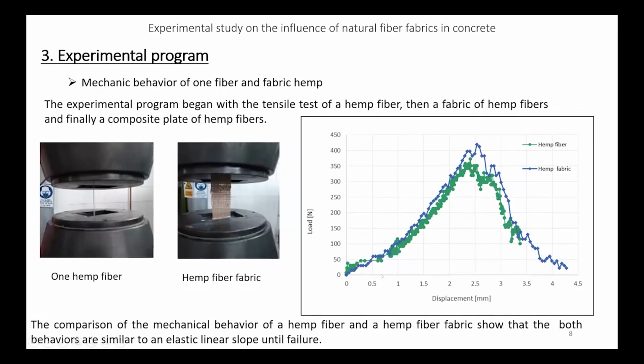You can see here some results for the tensile test of one fiber of hemp and of hemp fiber fabrics, and the comparison of the mechanical behavior presented in the curve here. You can see that the hemp fiber and the fiber fabric both show a similar behavior, an elastic linear slope until failure.